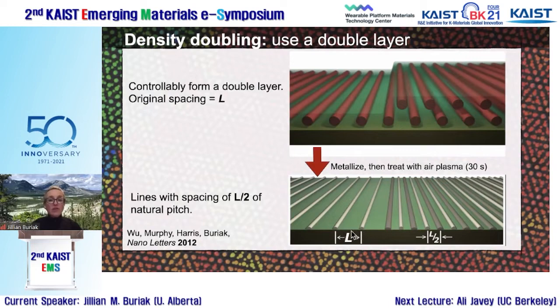So normally the block copolymer gives you its native spacing of L, but you can see that in the double layer in the top image there, these are a bit like putting two cylinders on their side, like paper towels or toilet paper. If you put them on their side, the lowest energy configuration, if you put another layer on, is at that interstitial space where they meet. And so when we metallize this, treat it with that simple air plasma, we're reducing the dimensionality from 2 to 1. And so that top layer falls between the two. And so you decrease the spacing between these two by a factor of 2. So the periodicity or the spacing, L, goes from L to L over 2.